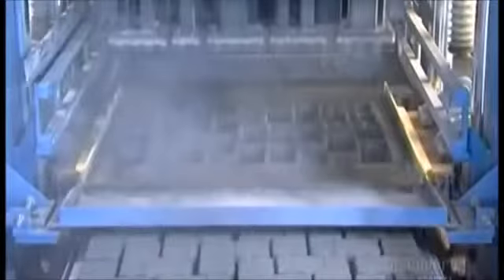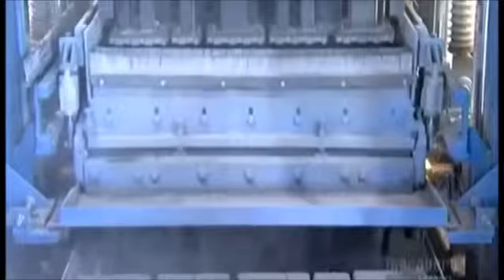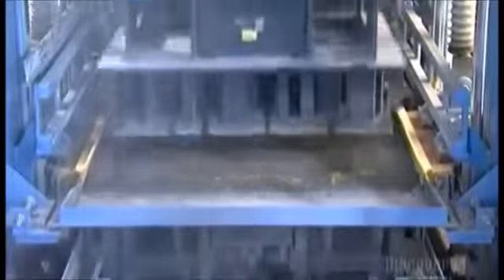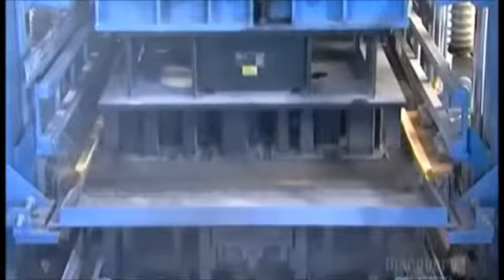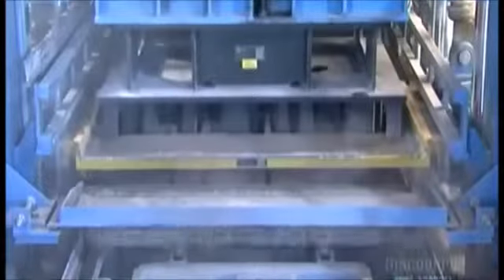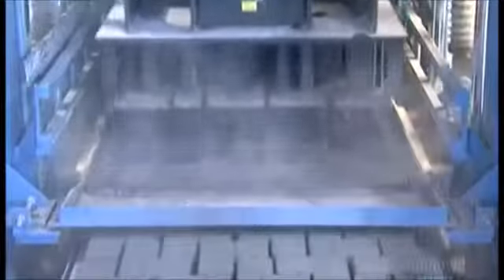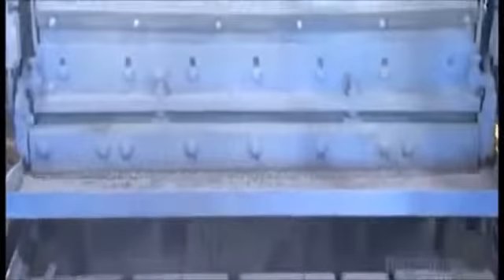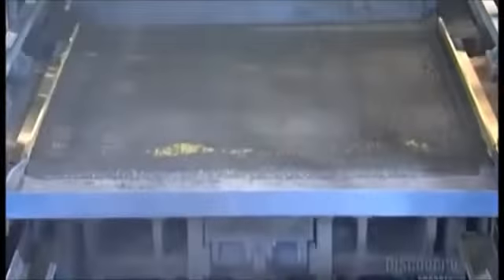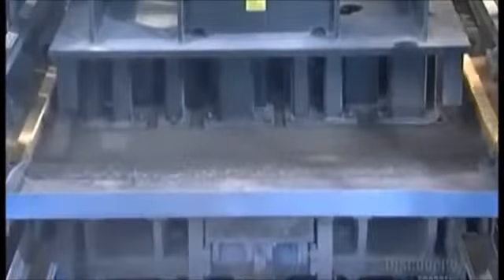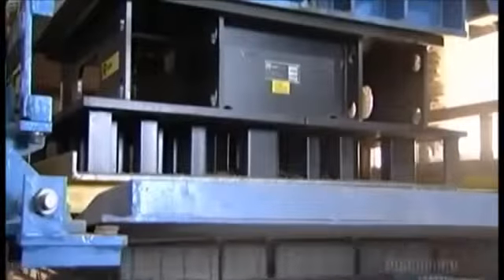Now a filling wagon spreads the mix over a steel mold containing up to 50 paver-shaped cavities. The mold press head applies 10 tons of vibrating pressure. This pulsating force compacts the mixture into the paver mold and removes any air pockets, which could weaken the pavers. Hydraulic cylinders lift the mold, leaving the pavers on the press board. The press board slides out and the mold once again gets filled in and makes another 50 paver stones. It only takes about 10 seconds to mold, compact, and release a batch of pavers.